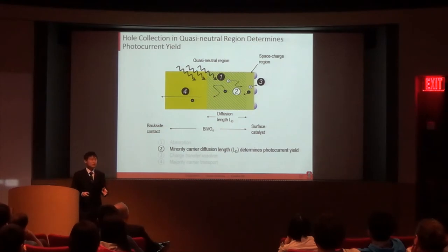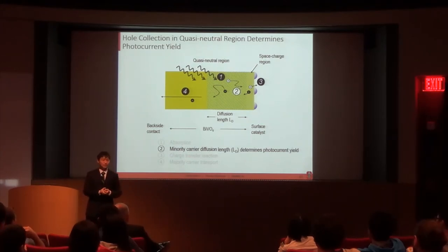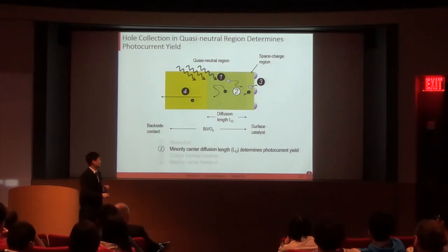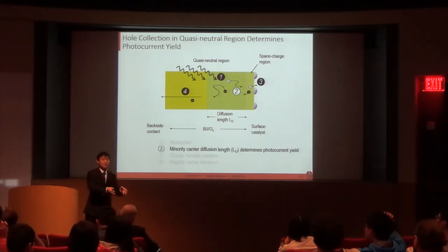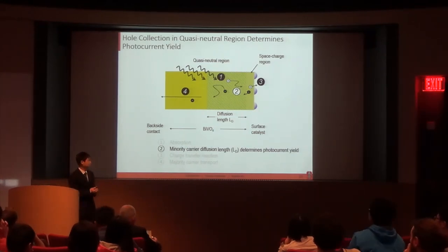And that means the thermal enhancement in the saturation photocurrent could be only due to the thermally activated minority carrier diffusion length. And we should note that any improvement in the minority carrier diffusion length means that the thermally enhanced minority carrier mobility must outweigh any decrease in the carrier lifetime, if there's any, with temperature.